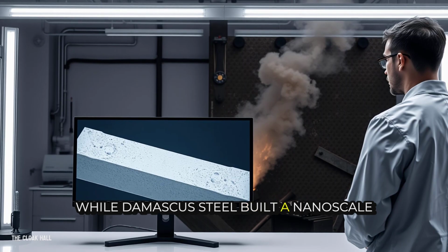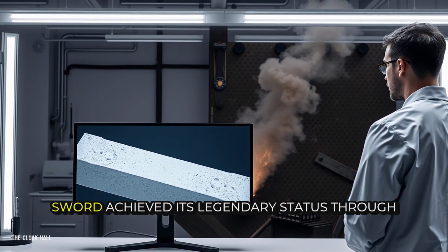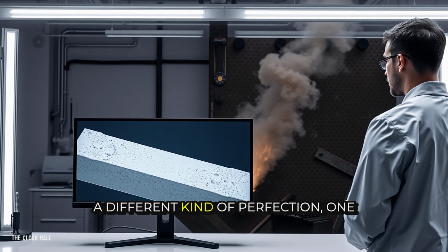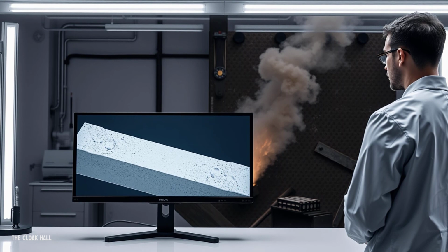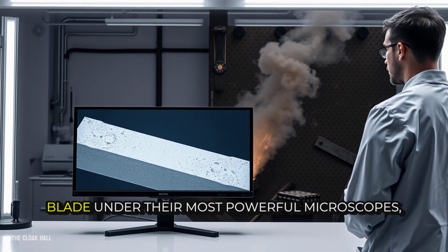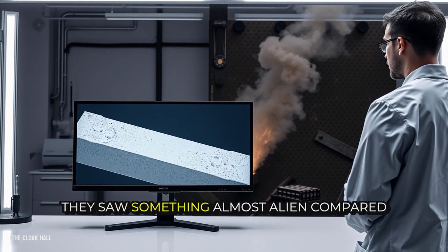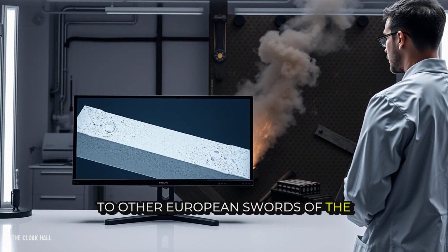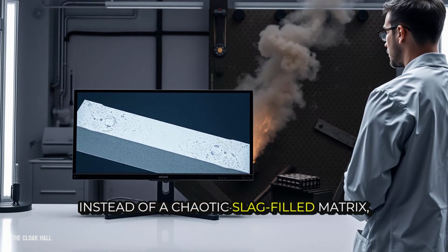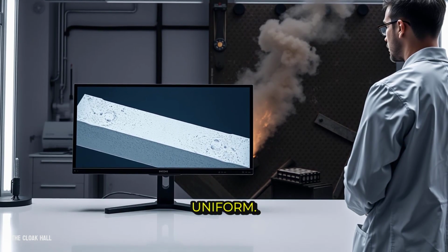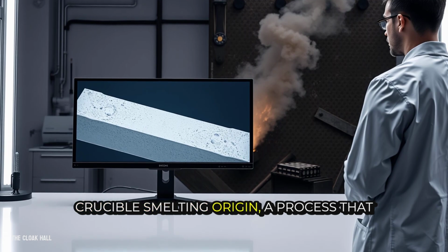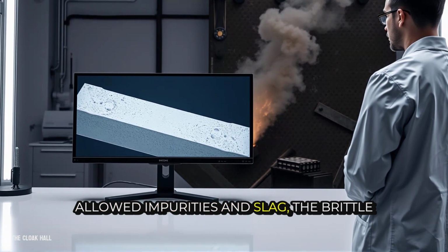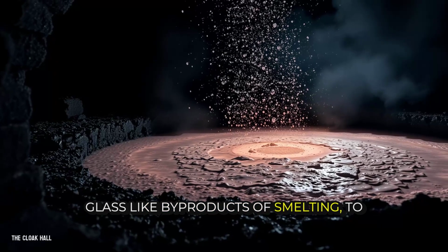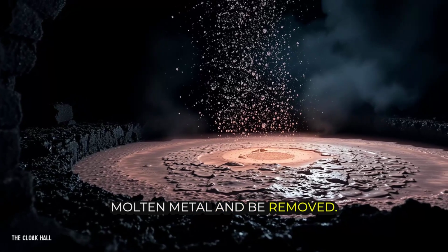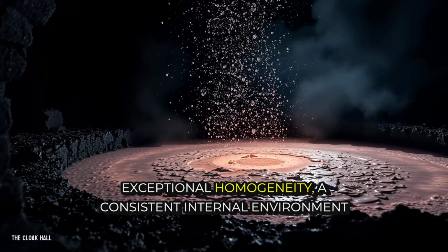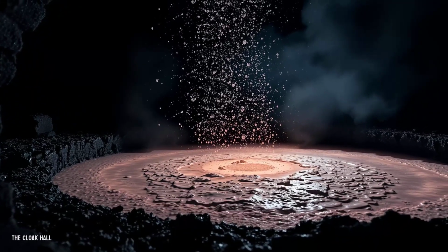While Damascus Steel built a nanoscale city within its layers, the Ulfbert Sword achieved its legendary status through a different kind of perfection, one of breathtaking purity. When researchers examined a genuine Ulfbert blade under their most powerful microscopes, they saw something almost alien compared to other European swords of the era. Instead of a chaotic, slag-filled matrix, the metal was stunningly clean and uniform. This was the result of its crucible smelting origin, a process that allowed impurities and slag, the brittle glass-like byproducts of smelting, to rise to the top of the molten metal and be removed. What remained was a steel of exceptional homogeneity, a consistent internal environment from edge to spine.